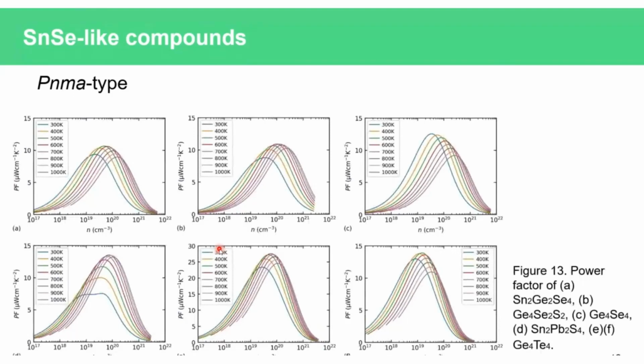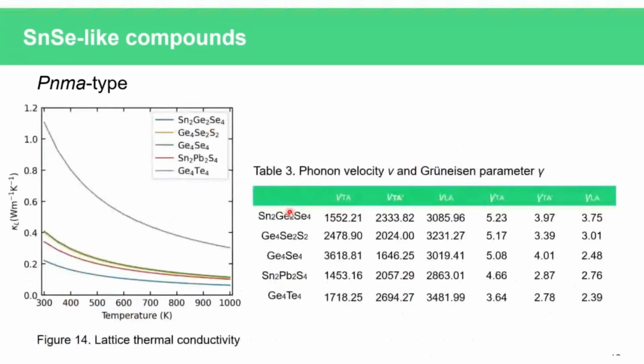According to our calculation, this group of compounds is better as N-type than P-type thermoelectric materials. Their N-type power factor could be higher than 10 microwatt per centimeter per Kelvin square. The exception is germanium telluride, whose both N-type and P-type power factor can be higher than 10. Compared with the power factor of those cubic compounds I introduced above, such power factor values are not so high.